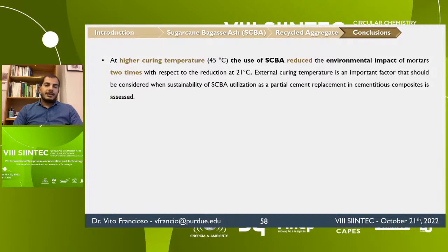So, the results of the first study on sugarcane bagasse clearly indicated the sustainability of sugarcane bagasse ash utilization as a partial replacement for cement, but also this is true for other biomass ashes. The benefit will be higher when mortar is poured in hot regions or during days where there is high temperature. Therefore, the external curing temperature is an important factor that should be considered when the sustainability of cementitious composites containing biomass ash is assessed.